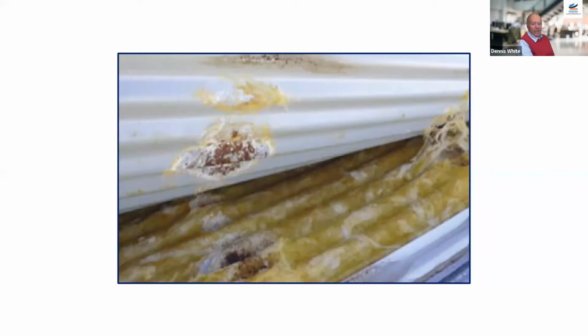And one must understand that anywhere where water pools, or if you've got a soil that's being compacted but is holding any form of moisture, you're effectively creating a steamer, which is the worst possible scenario, because you've got this fine mist that penetrates through capillary attraction into the tightly packed bundles or where you've got contact surfaces. The worst thing you can do, of course, is to store material under a clear or semi-opaque material, because then you're getting heat into it, and again, you're drawing and holding the moisture that's there.